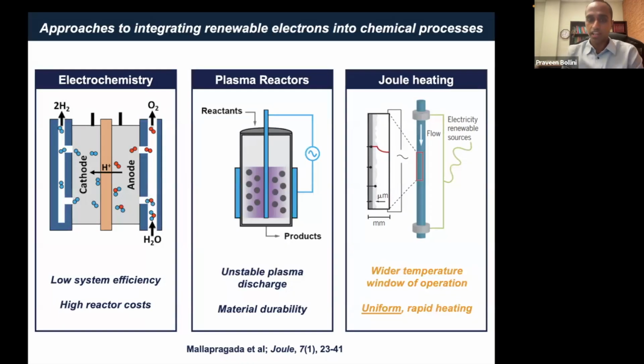A third approach, which is gaining increasing traction and which our department and my group are active in, is using joule heating to provide energy for heating endothermic chemical processes. Partly what this has been advertised as is a way of using renewable electrons while not changing the configuration or the scalability of the reactor, or not hampering that all that much. And one of the advantages that has been cited repeatedly is that you can get uniform rapid heating using electrified reactors.